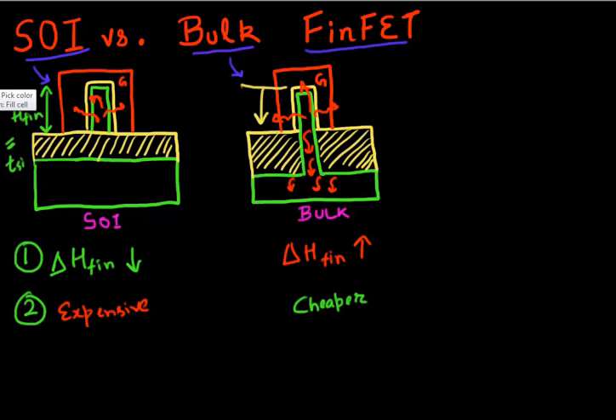On the other hand, if you are making your FinFET on a SOI substrate, oxide has a thermal conductivity which is 100 times lower than the thermal conductivity of silicon. So the thermal conductivity of oxide is two orders of magnitude lower than silicon. So it becomes pretty hard. The only way the heat can flow out is through these gate and through these contacts, but it's harder from a heat perspective over here. So clearly, SOI substrate, one of the problems is heat dissipation.